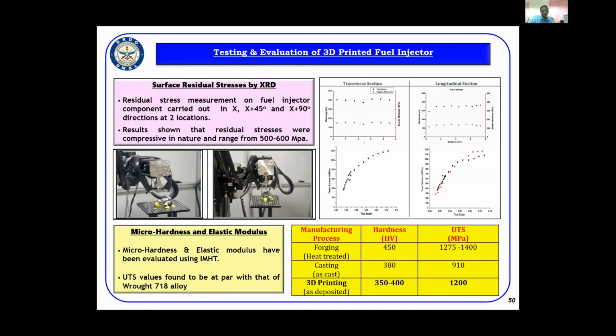We then went ahead to understand the residual stresses, because very high temperatures are involved in the deposition during 3D printing of components, and these residual stresses have to be relaxed. To understand what sort of residual stresses were present, we adopted the XRD approach and saw that the residual stresses were compressive in nature, as expected, in the range of 500 to 600. Micro hardness and elastic modulus were also measured using an instrumented micro hardness tester, and finally we could see that UTS values are at par with that of wrought 718 alloy. These are the various tests that have been carried out on this component.